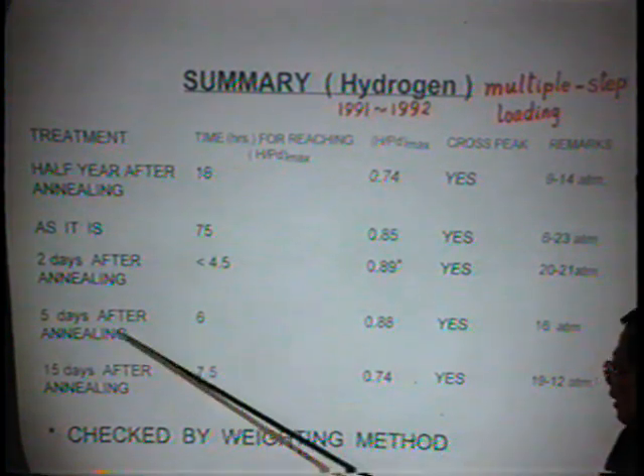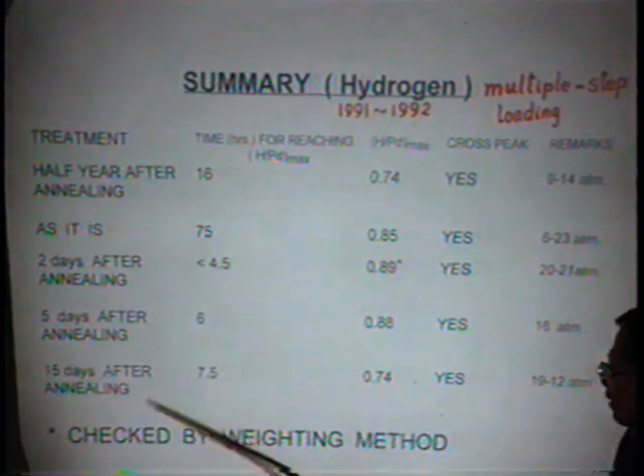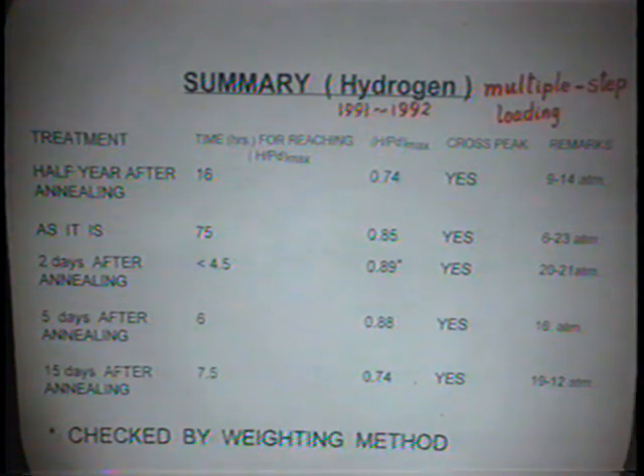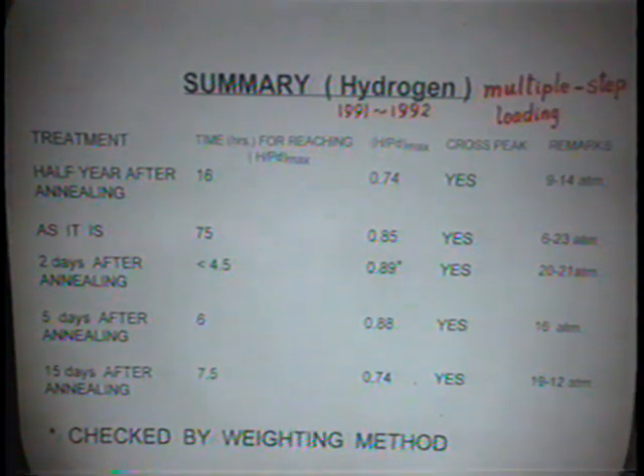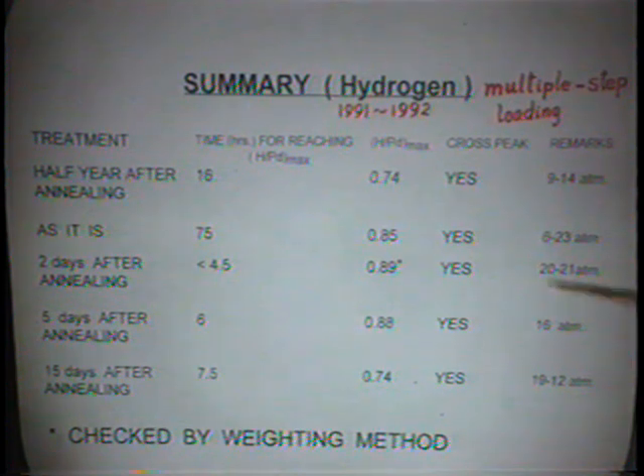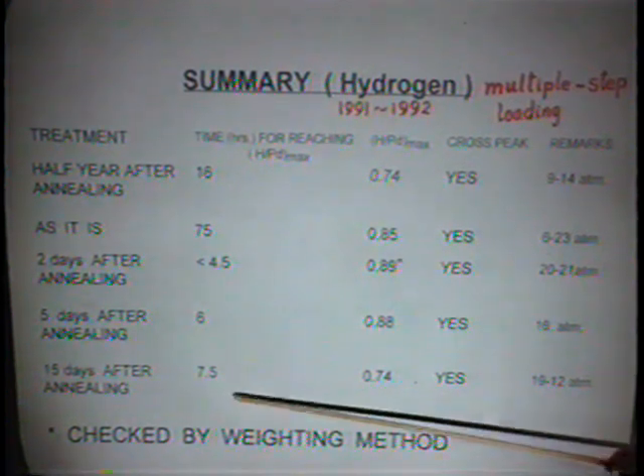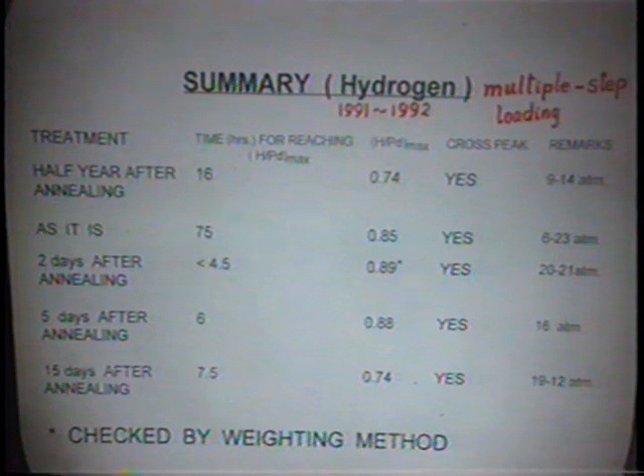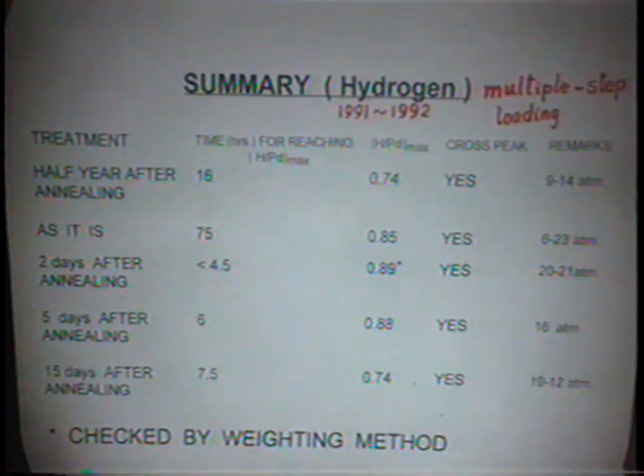5 days after the annealing is 6 hours. 15 days after annealing, more than 7.5 hours. Of course, the pressure control is not very good, so this is just a kind of reference showing the annealing will affect the rate.